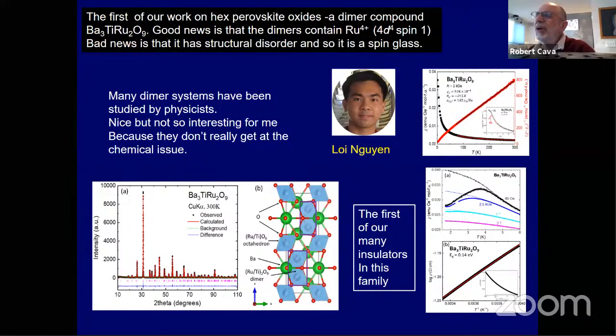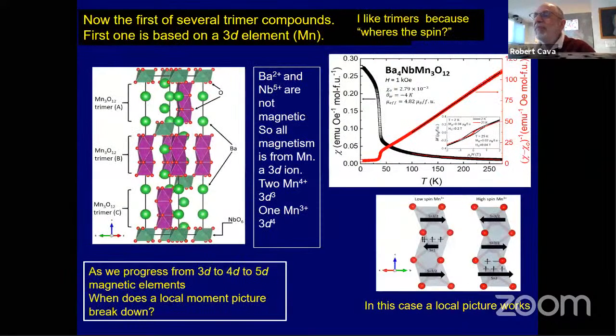The first one we did wasn't so interesting because it had titanium and ruthenium mixed in a hexagonal perovskite. What is interesting about this is that you get these dimers. So if you look sideways to the hexagon now, we have a distinct lattice of things and then a dimer lattice made up of something here. Now, unfortunately, titanium and ruthenium are similar enough that there's disorder in this thing. And so if you have titanium and ruthenium mixed, it's not interesting. What we want to do is make them unmixed. And there are some dimer compounds that are easily made that have been studied by physicists quite a bit. So that's good. But what's interesting to me is when they're bigger.